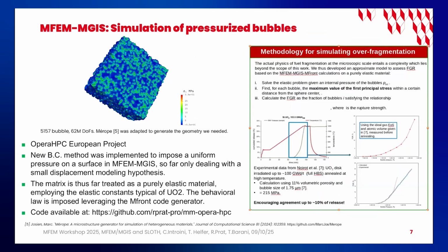So I will go a little bit further to another example of what we are able to do. In this example, we describe a representative elementary volume of nuclear fuel, and this is done by my colleague Tommaso Barani. And we try to model what can happen during fuel annealing after irradiation. What happens during irradiation is that we create bubbles with pressurized gases. And if we anneal the fuel, the pressure inside the bubbles increases, and then you have fragmentation of this RVE, which leads to release of fission gas products.